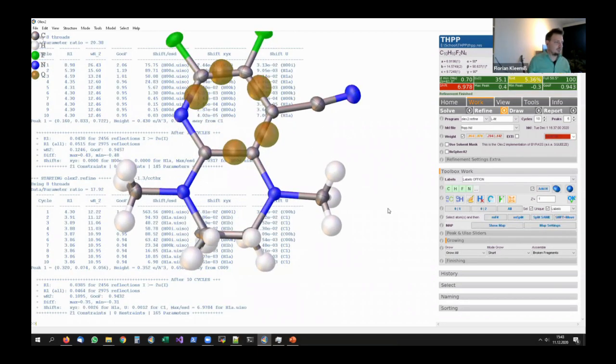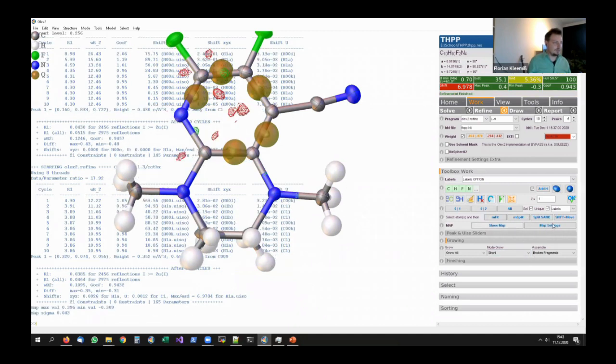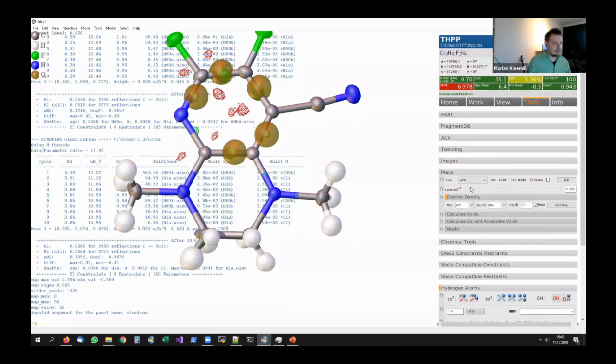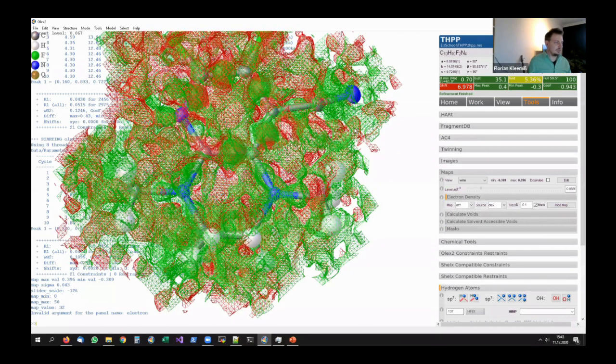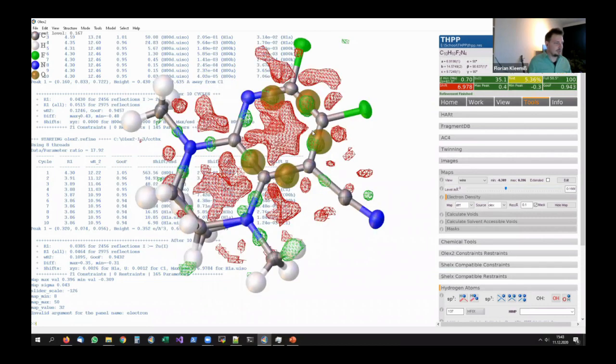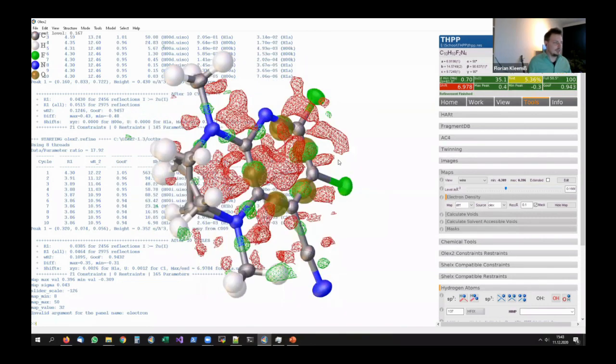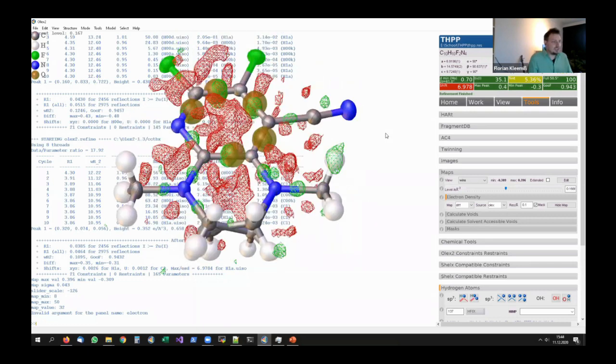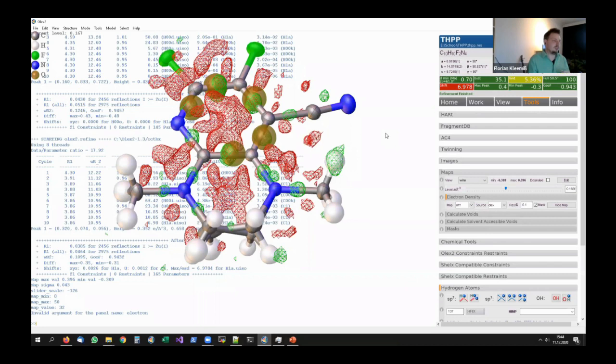And what you can see is the remaining Q peaks of our residual density map as well are located in bonding regions. Sorry, this was maybe a bit extreme. So as you can see, this is what you observe for a high quality measurement. In this case, the resolution is 0.7. It was molybdenum data. And I would say if you have a good enough crystal and a good enough setup of the diffractometer, it is really very possible to measure this kind of data sets